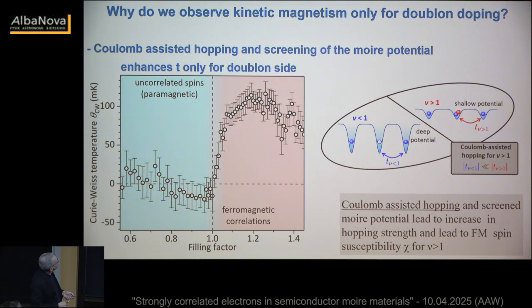So given time, I'm not sure if I should tell you, there is actually also very interesting anti-ferromagnetic physics expected on the hole-doped side. We don't see it, and we have some idea as to why this should be: because of the strong interactions, we modify the moiré potential beyond nu equals 1. So we basically have a Hartree-Fock moiré potential.